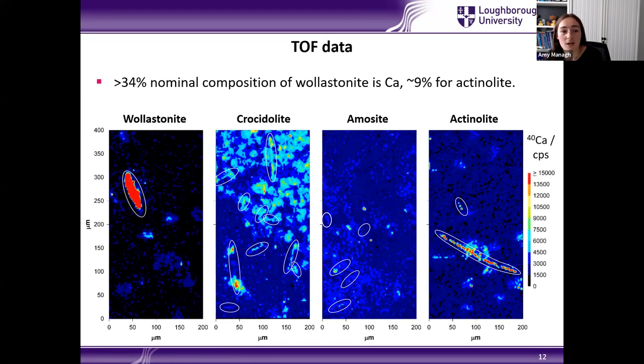We then moved on to look at calcium. So this is an element that we weren't able to look at using the sector field technology. We see quite a large signal for wollastonite. Over 34% of the nominal composition of wollastonite is calcium. So this was expected. 9% of actinolite is calcium as well. So we see a strong signal there. And we didn't see any signals for the crocidolite and the amosite samples as we expected. So looking at calcium is able to distinguish these two fiber types here from the wollastonite and the actinolite.